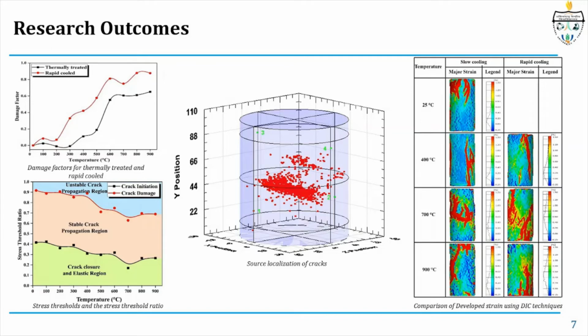Upon exposure to high temperatures, the crack initiation stress threshold ratio and crack damage stress threshold ratio follow a decreasing pattern, which indicates the early occurrence of both the crack initiation and crack damage event in the thermally treated sandstone. Also, a comparison between the Aramis images of thermally treated and rapid cooled specimens suggested clear development of well-distributed, more significant strains for rapid cooled specimens than thermally treated specimens.